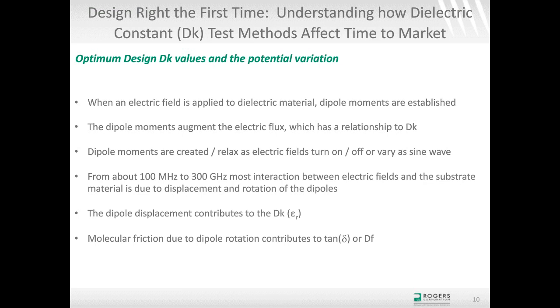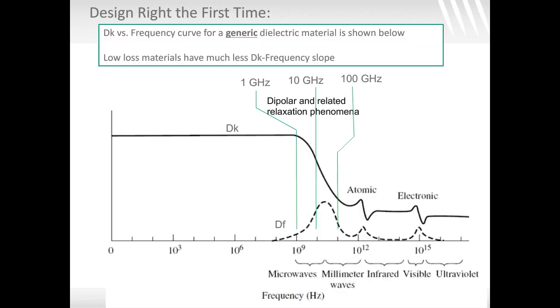And then what you get is a curve shown here that's out of basically a material science text. And it's showing that in the range of frequencies that we're interested in, normally the microwave, lower millimeter wave range, there is a change in dielectric constant with a change in frequency, higher frequency, lower dielectric constant. This is actually a generic curve, though, for a generic material anyway. Most of the high-frequency circuit materials have that same trend, but a lot more gentle slope.